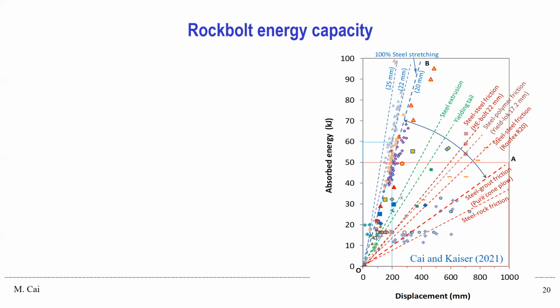Rock bolts with this yielding mechanism will follow this line. And line OB is the line for pure steel stretching for a steel bar with 20 millimeter diameter. So test data will mostly follow along this line. If you have larger diameter bolts, they will be on the left of line OB. For other friction bolts, if it's a steel-rock contact friction, it will be less than the steel-steel contact friction, and the test data will be on the right of line OA.